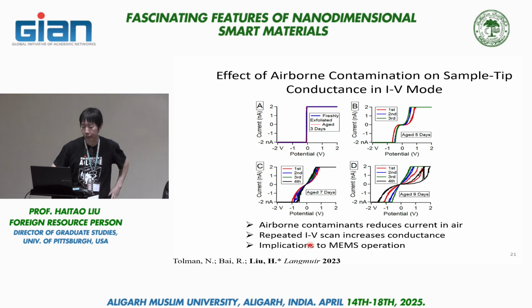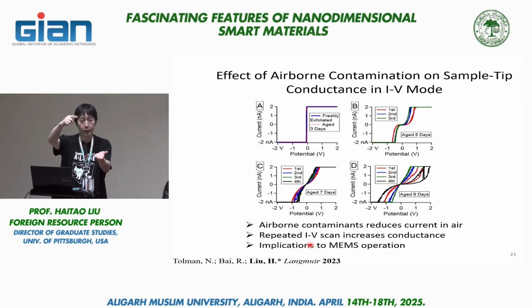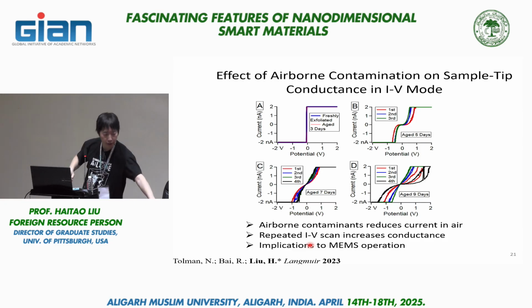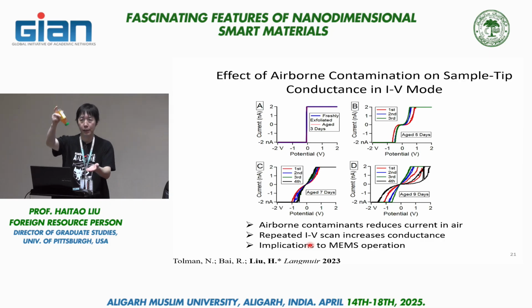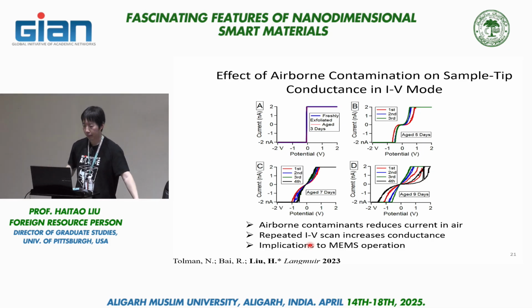To illustrate that case, I show a bunch of current voltage curves. So what we did here, again, is we have this AFM tip, and this is my graphite substrate. And we push the tip to the surface. And when there's a contact, we apply voltage between the tip and the substrate, and then we measure the current. Very easy. So we do this in different environments.